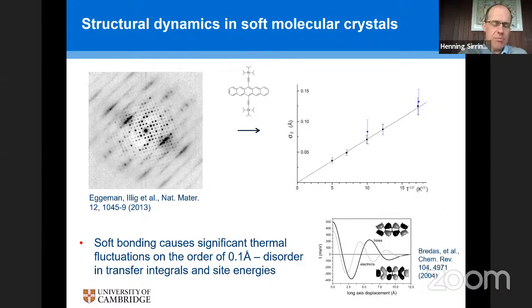And so this is a transmission electron diffraction pattern that you see here on the left. It is from a study that we undertook a few years ago, where we were trying to investigate the single crystal structure of this particular molecule that you see in the middle here. And you can see these sharp diffraction spots that indicate the crystalline molecular lattice, but you also see these diffuse streaks, very pronounced in the diffraction pattern. And it turns out that these diffuse streaks are manifestations of fairly strong thermal lattice fluctuations.